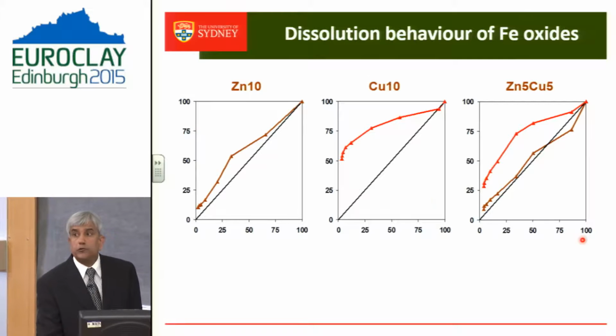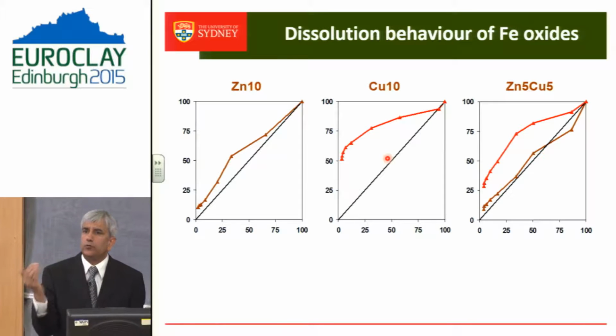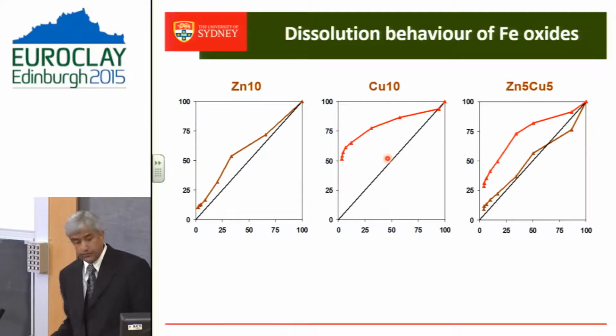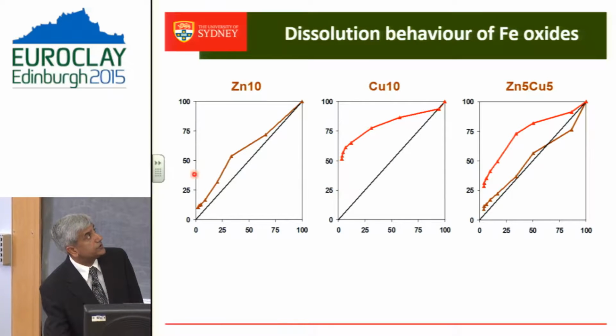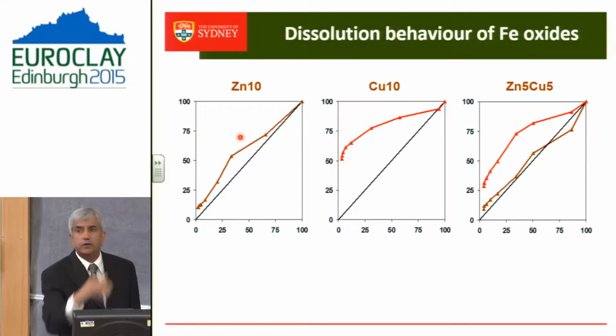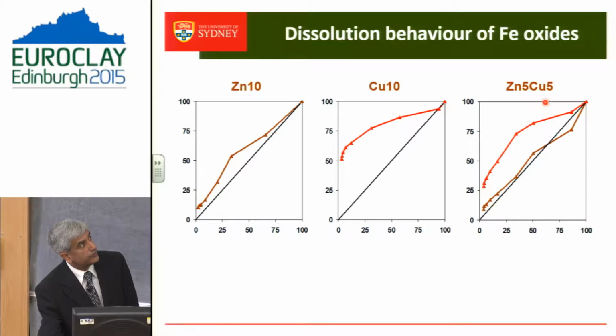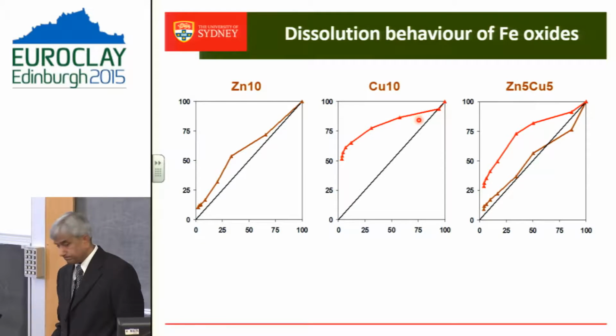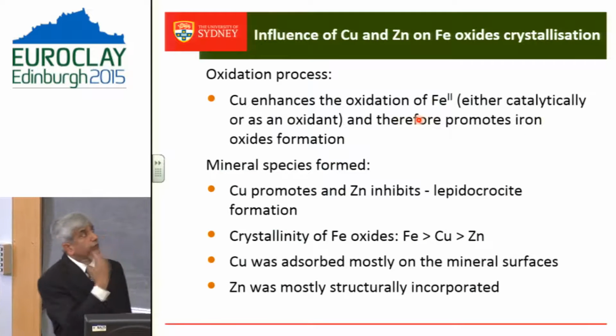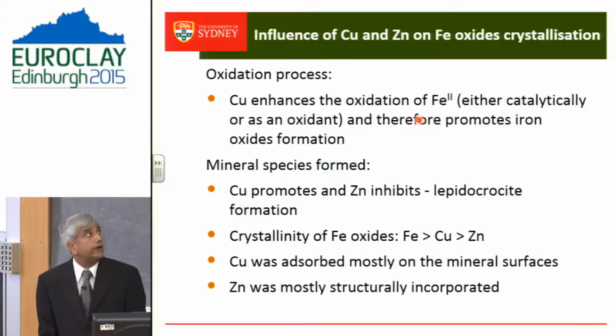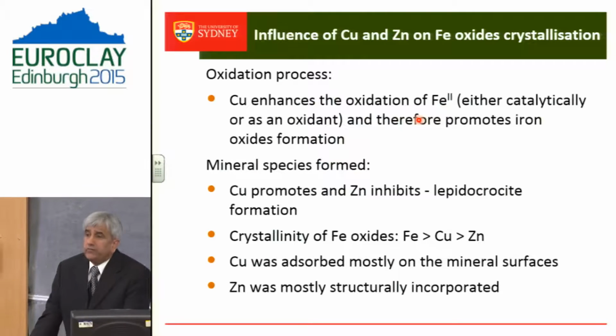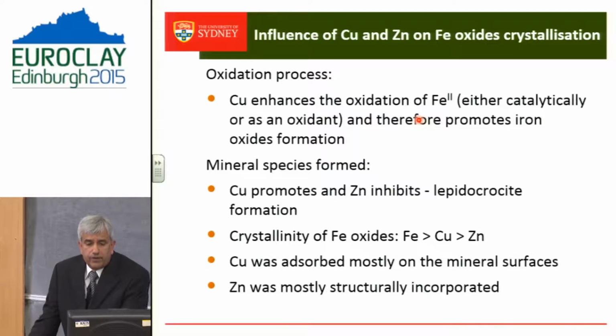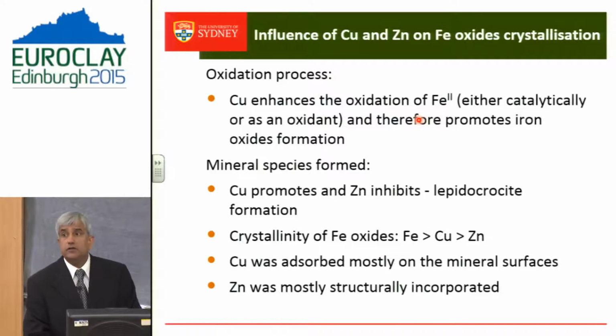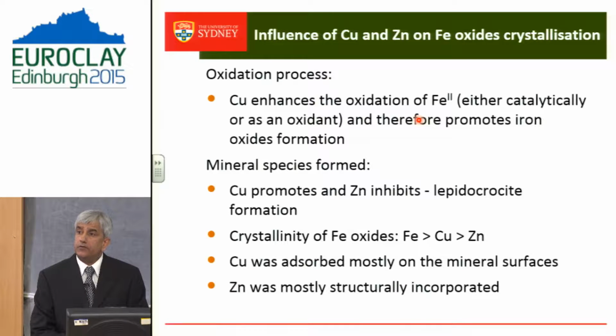That was also clear when we dissolved those samples: a lot of copper appeared well before iron, so it was predominantly adsorbed on the surface rather than in the structure. Whereas in case of zinc, as you can see, the dissolution is more or less fairly close to the 1:1 line. And in the combined system also, it's a lot closer to the 1:1 line than the pure copper system. So what we are seeing here is that copper obviously is enhancing the oxidation of iron, and in that process it affects the formation of a different phase than goethite.